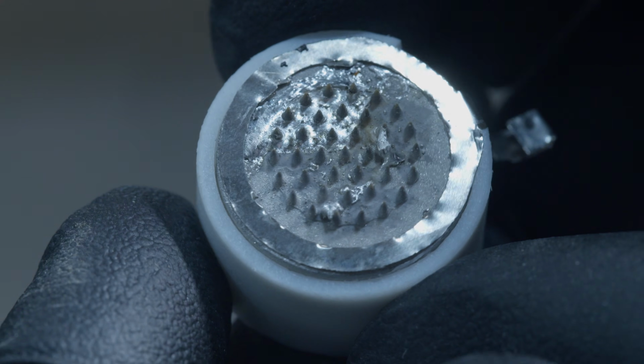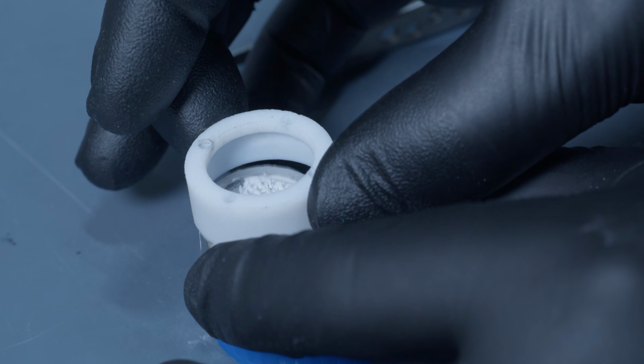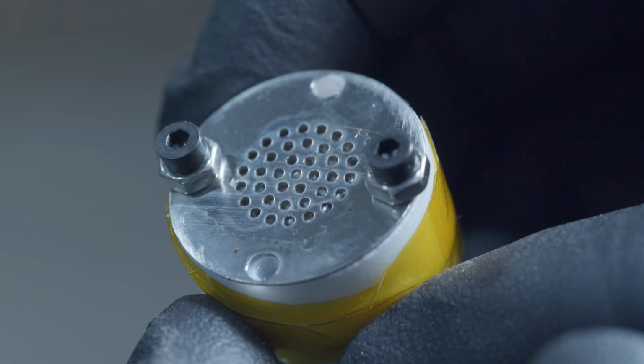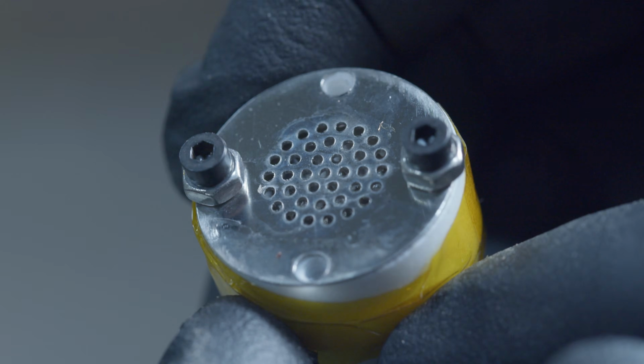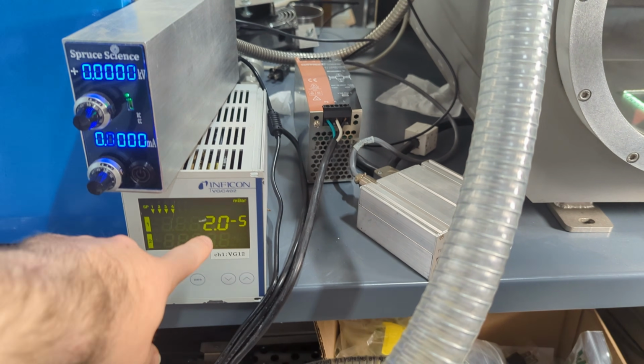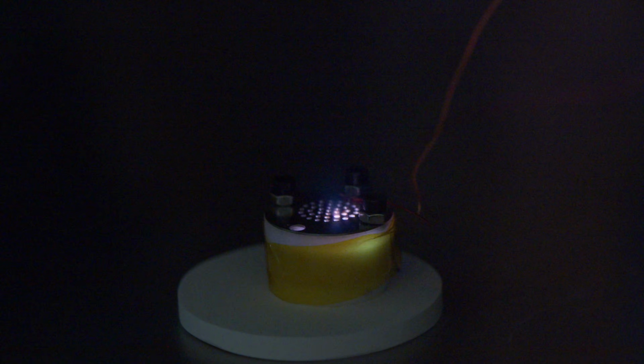I figured it was probably good enough to at least test it, so I made up a Teflon base, then a second electrode was aligned over the top of the tips, and it was placed inside the vacuum chamber for testing. We pump down to 2 × 10⁻⁵ millibars and begin applying high voltage. Not a whole lot happens as the voltage is slowly raised until suddenly we get a bunch of fireworks. And then nothing else. The device seems to have died. But how cool is that, right? I mean, this was my first attempt and the results looked super promising already.